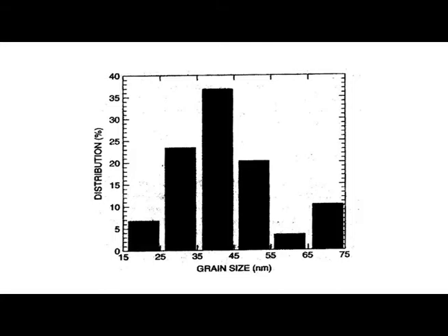This is a bar diagram showing the size of the particles against their percentage distribution that we have obtained from the synthesis. It is seen that the largest fraction of particles is having a grain size of about 40 nanometer in a range of 20 nanometer to 70 nanometer.